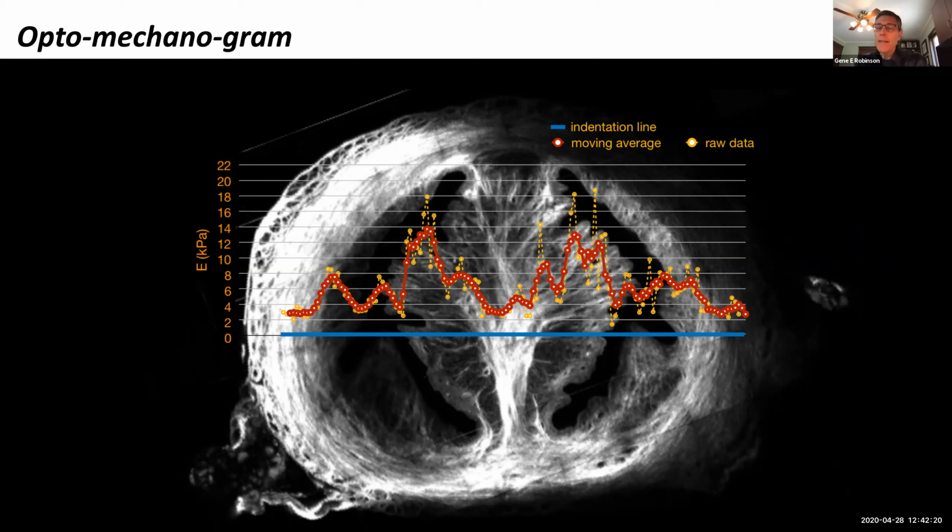Next question, is it possible that nanoindentation performs worse on fibrous materials, thus explaining the observed difference in stiffness? So I'm not sure what worse means for mechanical testing, but I think one of the contributors to the difference in stiffness is that we can only see the collagen. And there's another important constituent there called glycosaminoglycans. Glycosaminoglycans are known to be a constituent that behaves differently in compression and tension, and similarly fibers behave differently in compression and tension. So GAGs are an important component of, say, cartilage, which has really good behavior in compression.